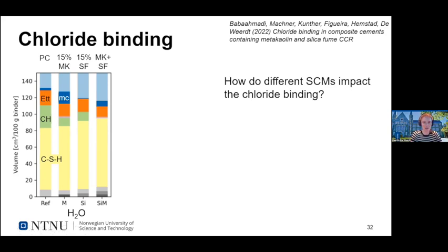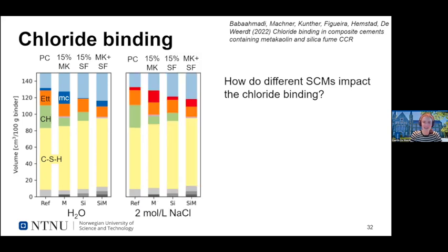And then I used GEMS, or Arizu used GEMS, to calculate what happens if we expose these systems to sodium chloride. And we used a high concentration, 2 mol per liter. And we looked at what happens with the hydrate assemblage. And when you compare the figures here on the left with the ones on the right, the main difference is actually that the blue boxes turn red. And the red is Friedel salt. So it's actually in the same family of monocarbonate, but instead of containing carbonates, it contains chloride. So GEMS predicts that most of the AFM goes to Friedel salt.